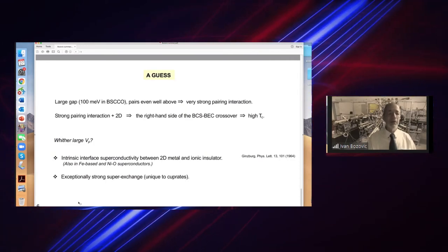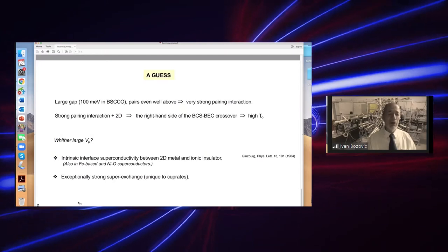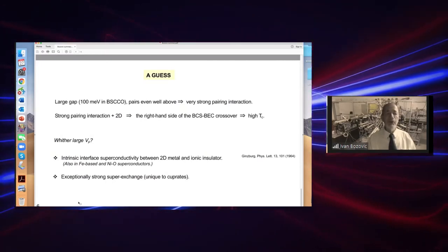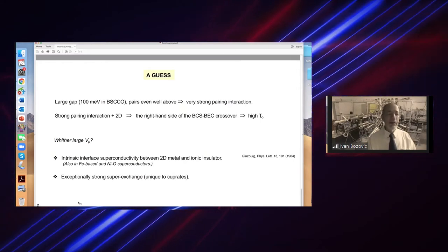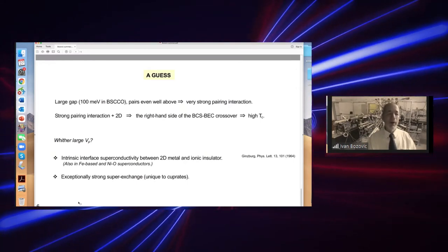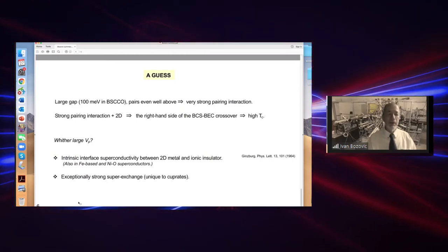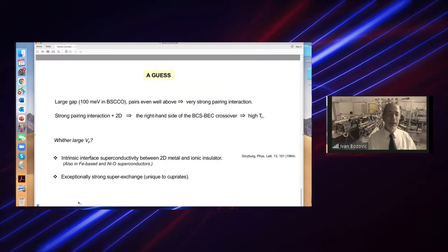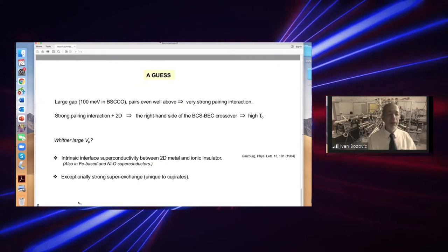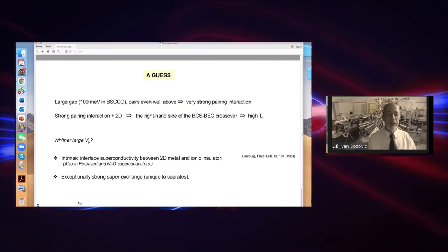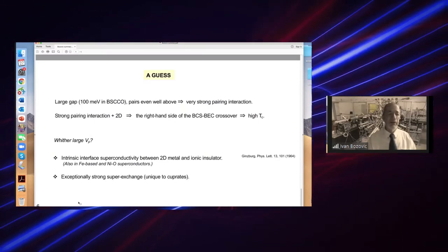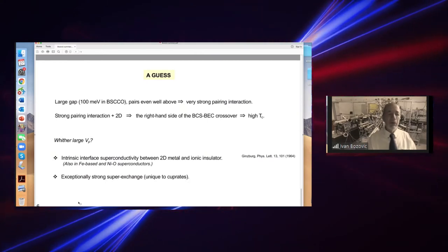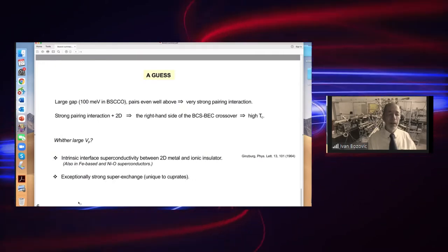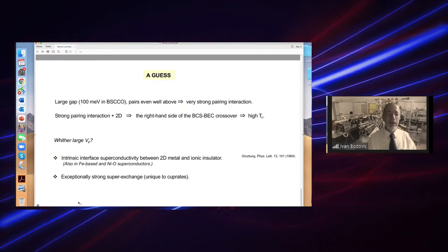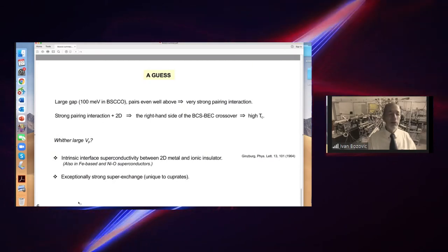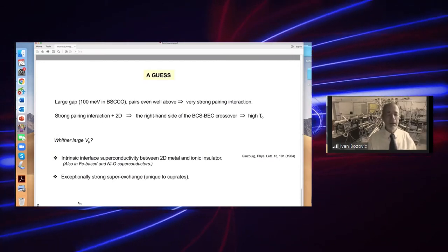Now, a more tricky question is why the pairing interaction is so strong to begin with. And I guess, again, for two reasons. One is that cuprates are native metal-insulator superlattices, and superconductivity is therefore interfacial between the metal and the ionic insulator. The second reason is chemical. The copper 3d and oxygen 2p levels almost coincide. This is an almost unique occurrence in the periodic table. And this is the reason why superexchange is so exceptionally strong in cuprates compared to other oxides and other materials.